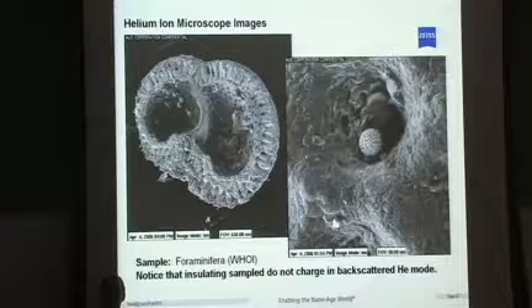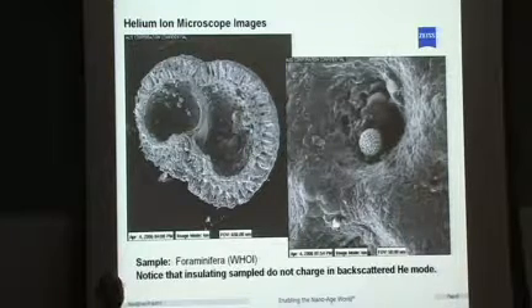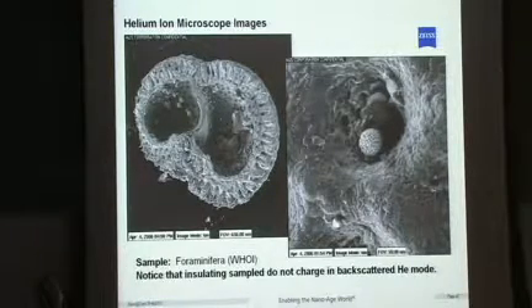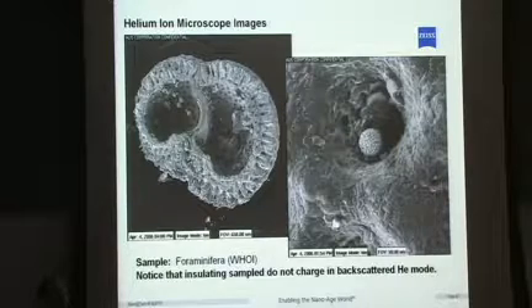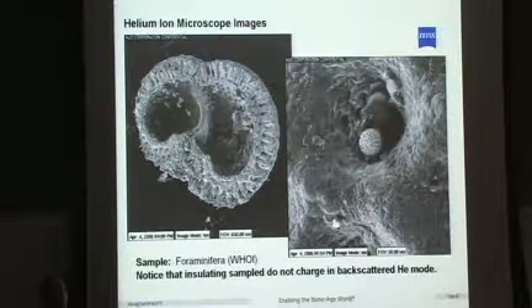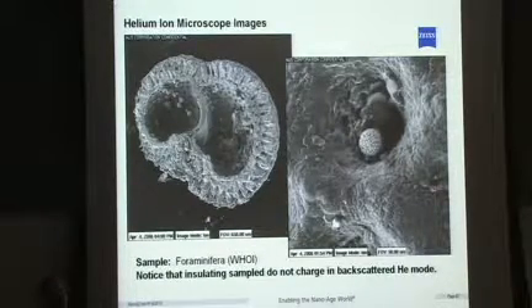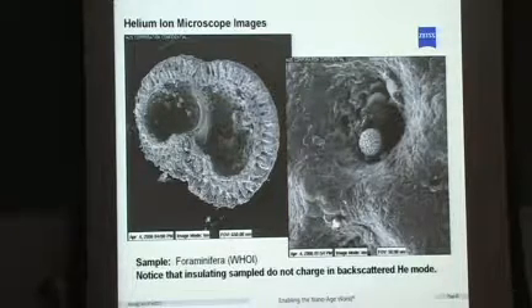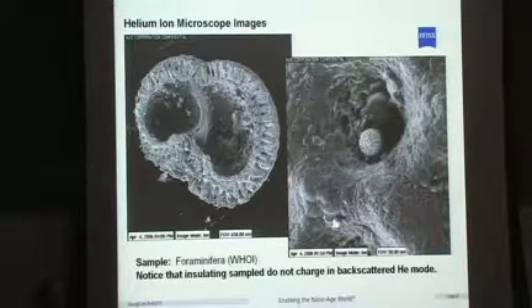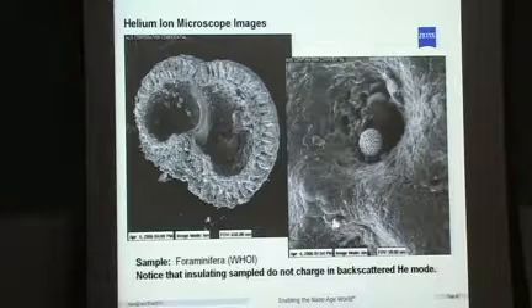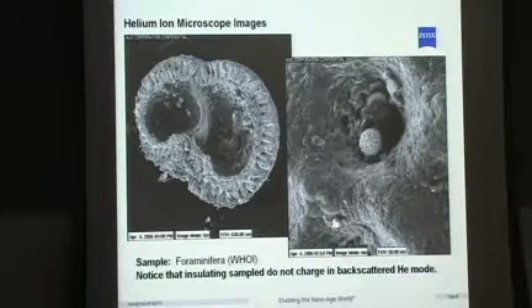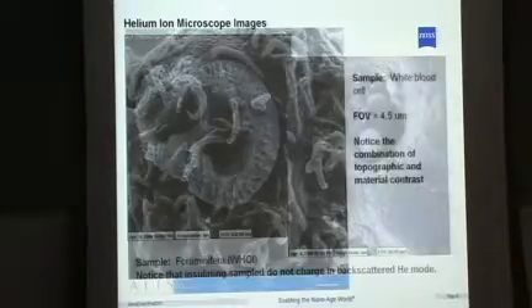So any charging that happens is right at the surface. That's perfect for an electron flood gun, which can solve that problem quite easily. Compare that to a SEM, where the electron beam goes in sometimes quite deep. In an insulator, that charge can't be just solved by a flood gun. It's very tricky to get out subsurface deposited charge. We have a unique advantage in that regard.